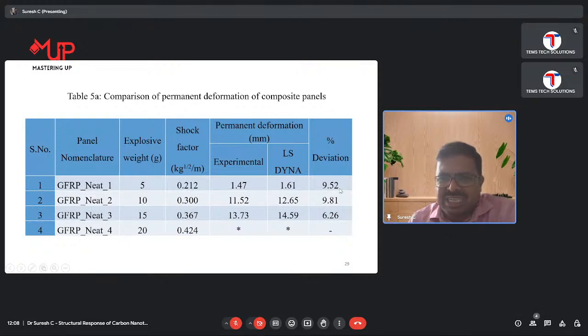For engineering accuracy, if the deviation is less than 10 percentage, it is acceptable. So our deviation is less than 10 percentage, so we accepted it and we continued with the numerical simulations for all other parametric studies. Next, for 10 gram, experimentally the deformation is 11.52 mm, and from LS Dyna it is 12.65 mm. Deviation is almost close to 10, but it is less than 10.